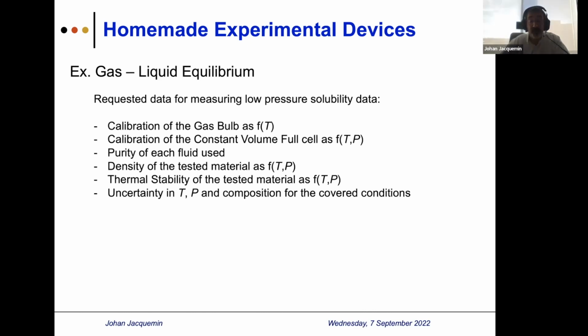You need to determine the purity of each fluid, and also be sure that your non-volatile liquid is dry first, especially for porous material or ionic liquid, and also well vacuumed to avoid any trapped gas, which may be possible in a very viscous solvent. And we must know the density. That's also a big problem, because density must be known in the volumetric techniques. And the density, I would say, as a function of temperature and pressure, and also, if we have very high solubility, and if we expect or suspect chemisorption, we must determine the density before and after CO2 or gas solubility.